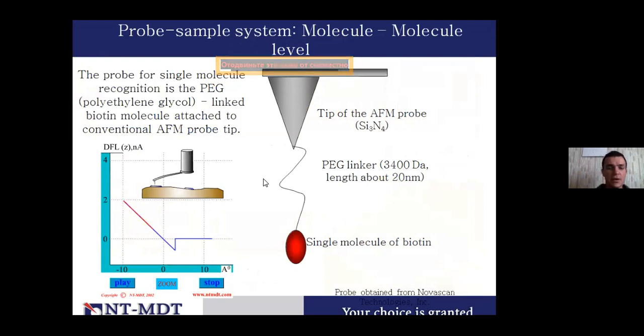In the beginning, I mentioned one interesting application to study single molecule interaction. And here is the principle of how it works. We use the AFM probes, we use some linker and attach some biotin molecules to the end of the tip, just single molecules. And then if we have some surface and some distribution of other molecules, then from the animation on the left, you can see how we can study this interaction. We approach different areas and see this interaction, and depending on the deflection curve, we have a different shape of the curve. In one case it is a big interaction, in another case it is smaller. And since we know that the cantilever is modified by this single molecule of biotin, we can understand even the force of interaction. So now let's switch to the next slide.